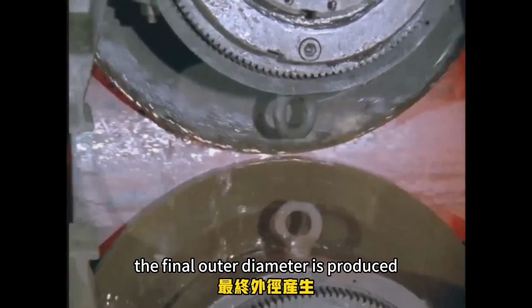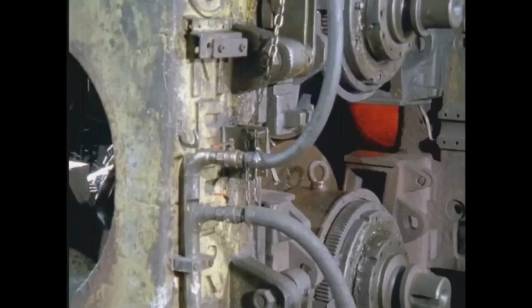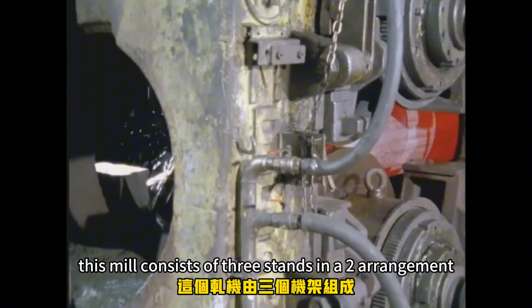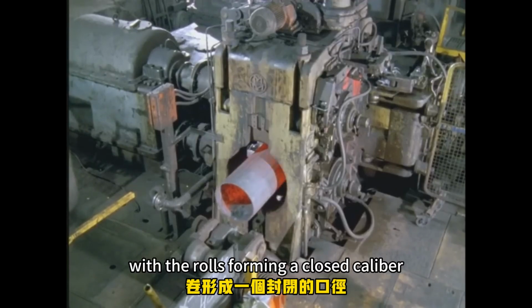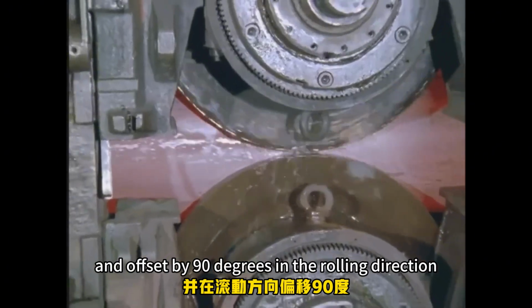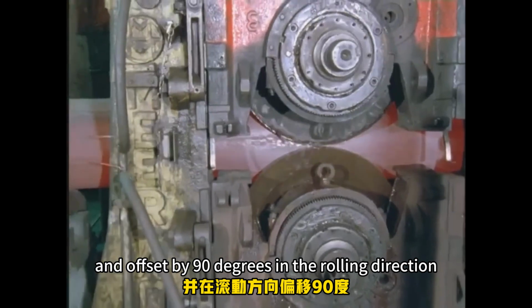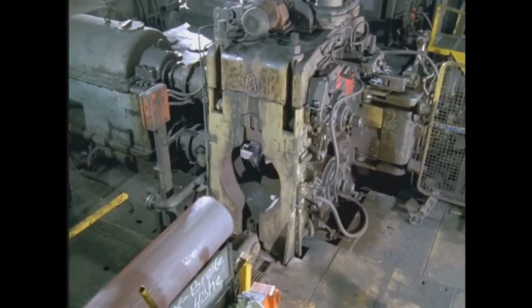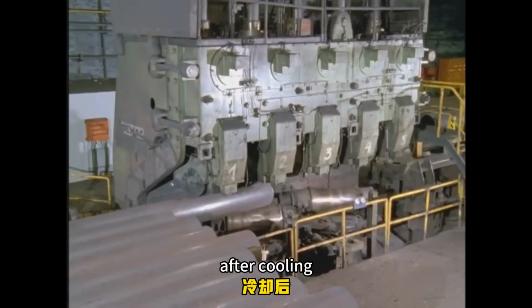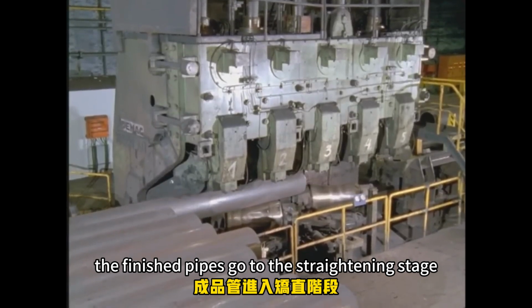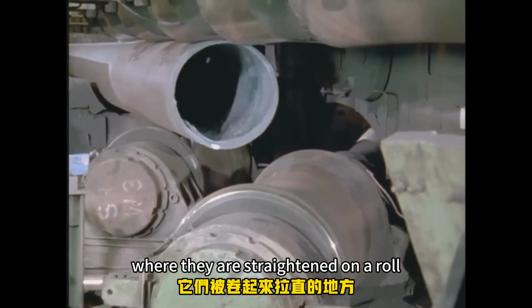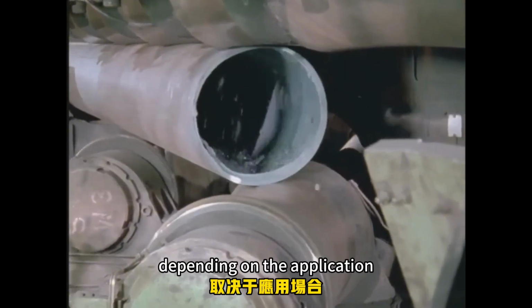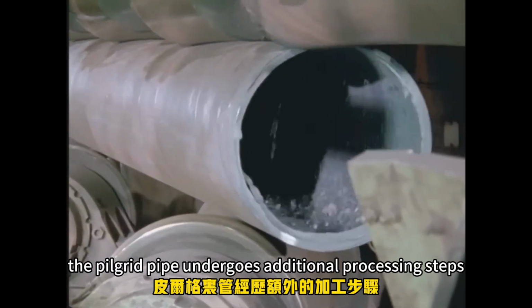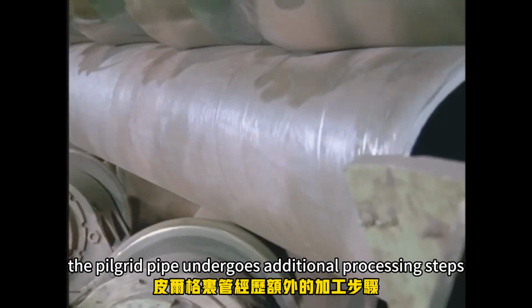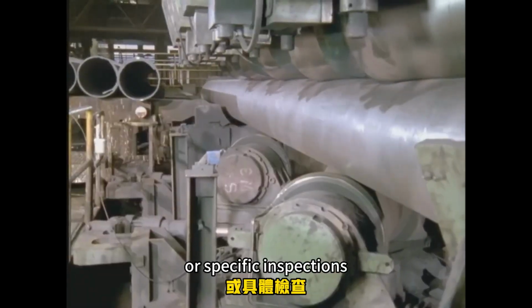In the stretch reducing mill, the final outer diameter is produced. This mill consists of 3 stands in a 2-roll arrangement, with the rolls forming a closed caliber and offset by 90 degrees in the rolling direction. After cooling, the finished pipes go to the straightening stage, where they are straightened on a roll straightening machine. Depending on the application, the pilger pipe undergoes additional processing steps or specific inspections.